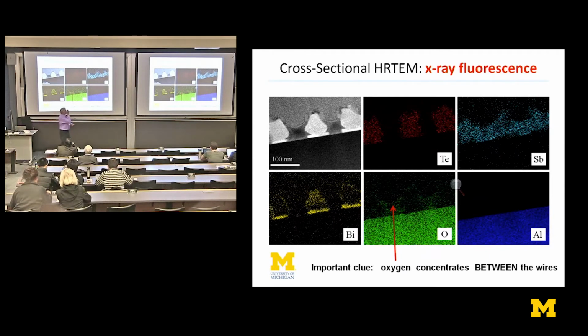So one of the things you can do with cross-sectional high-resolution TEM is you can look at the chemical makeup of the nano features element by element. Here's a map of tellurium, as you'd expect, within an antimony telluride structure. Tellurium, antimony, bismuth, and crucially here, oxygen.